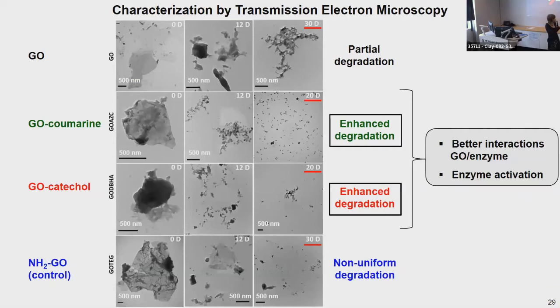So you see some holes in the sheets. While already after 20 days for the sample of graphene oxide functionalized with coumarin or with catechol, we could not see any sheets on the TEM grid. We could see only debris. So showing that the degradation was conclusive and was enhanced.